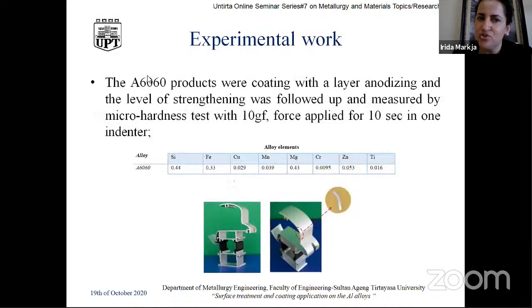The series of products used is 6060, and I have shown the chemical composition of the elements of this series of aluminum. The hardness, or micro hardness Vickers, is tested with 10 gram force, and the force is applied for 10 seconds in one indentation, for each measurement.